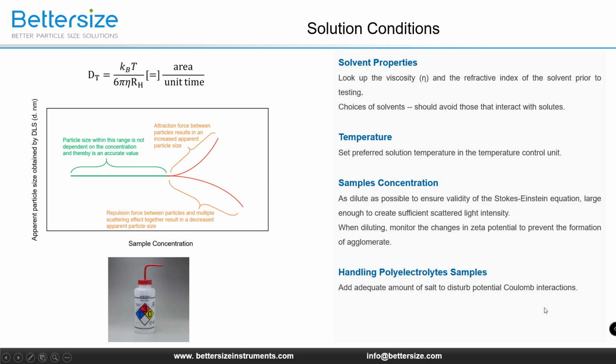The most important step in preparing a sample solution is to remove impurities such as dust particles. These impurities also undergo Brownian motions in solutions and will contribute to scattered light intensity, which will lead to an overestimation of size. To remove the dust particles, rinse the solution containers thoroughly with acetone and air dry it in a dust-free fume hood before transferring the solutions into the container.